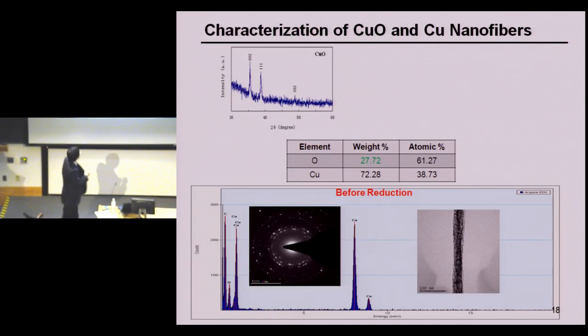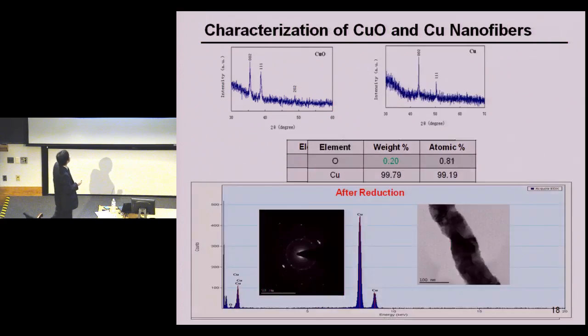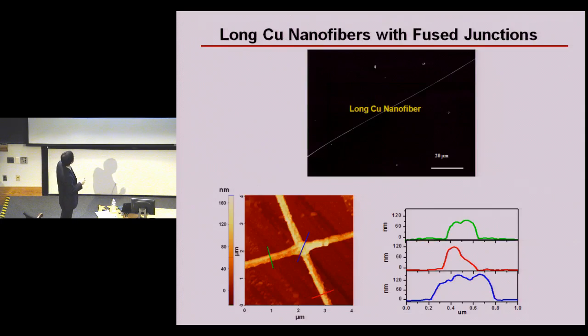So this is an XRD, and here it shows we have oxygen content before the reduction, and this is polycrystalline. After the reduction, we see here the oxygen content reduced down almost to zero, and this confirms the reduction indeed happened, and we get polycrystalline copper nanofibers. And it's very long, and also due to this high temperature process, the junctions are actually fused. So basically, these two allow us to achieve very good performance in terms of conductance as well as transparency.